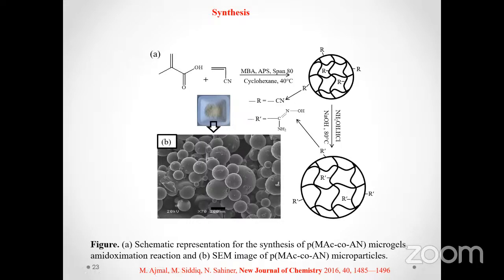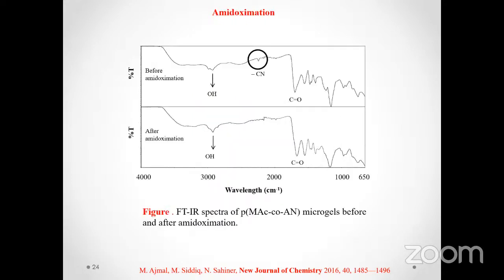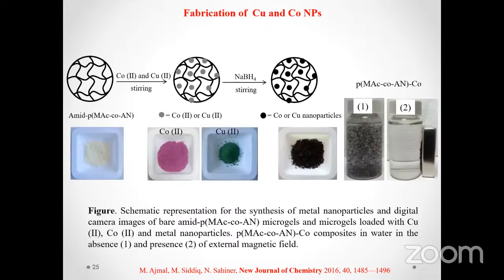around 200 micrometer. And this conversion of the nitrile group into the amido oxime group was verified by using FTIR analysis, and it was observed that after the modification, the nitrile functionality in the hydrogel disappeared, and it was an indication that the nitrile group has been converted into the amido oxime.